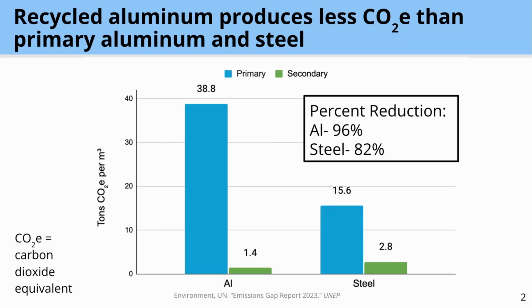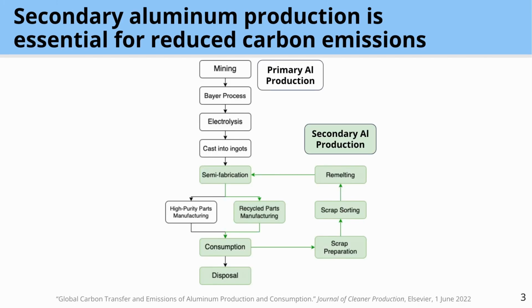So a little background on this project: recycled aluminum produces significantly less CO2 equivalent than primary aluminum and steel. As you can see, from primary aluminum to secondary aluminum, there is about a 96% reduction in tons of CO2e per cubic meter. This is very important because it shows secondary aluminum is much more cost and energy efficient. And this is primarily because secondary aluminum has a much smaller production process than primary aluminum.